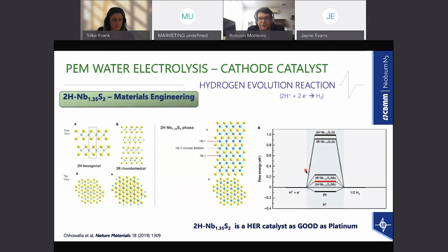If you jump to an even better material, this is the topic of Professor Chhowalla. Just to give you one spoiler of his presentation: Professor Chhowalla took this material to a new level. One of the problems of these transition metal dichalcogenides is that they are layered compounds. In between layers, there is quite a bit of loss in electronic conductivity, and they act as a dielectric layer. You can further improve this material if you put more niobium in between the layers, which is what Professor Chhowalla did. He did excess niobium insertion in the phase of hexagonal niobium disulfide, so you have an excess of niobium in the structure of the material.